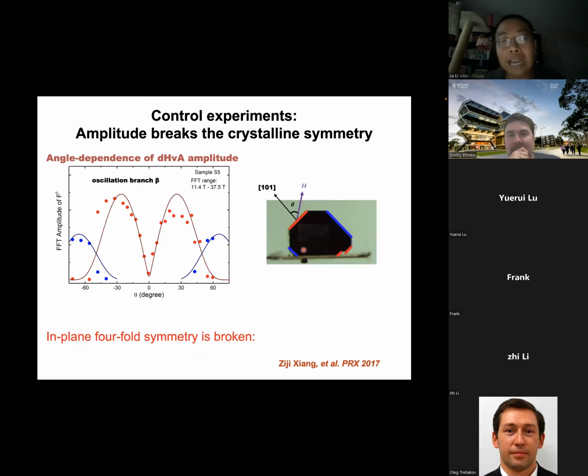But what shocked us was that once we looked at the oscillation amplitude, they seem to favor one direction over the other one. Red is larger, way larger than blue, which is 90 degrees away, just another family of the same crystalline symmetry. Okay, thank you. So that's really positive, right?